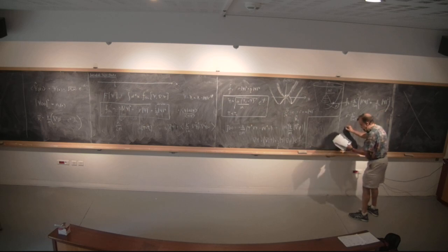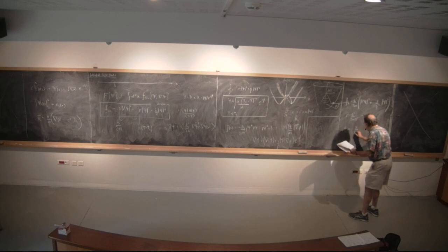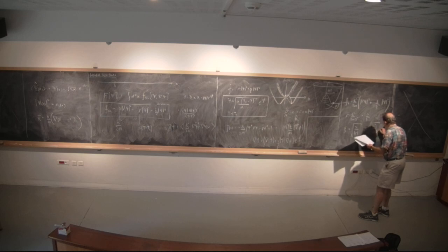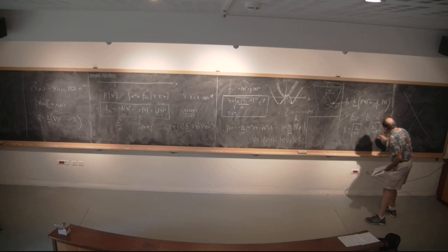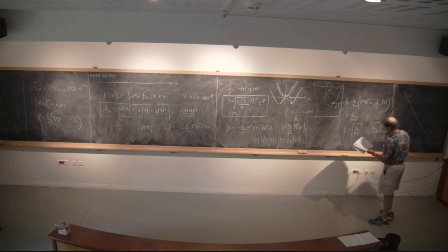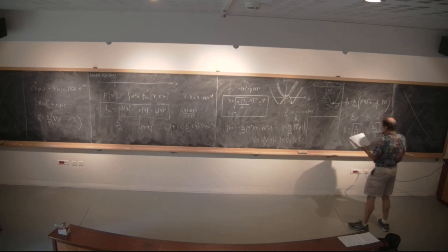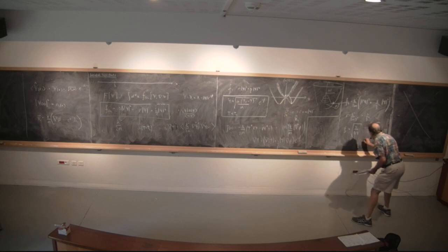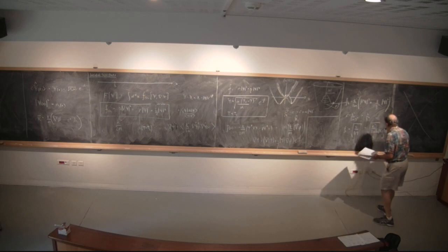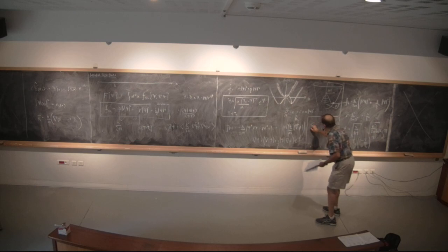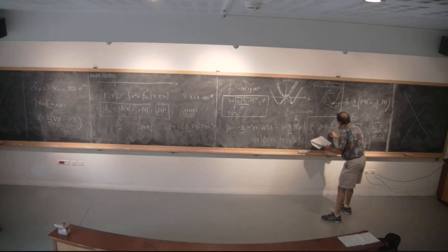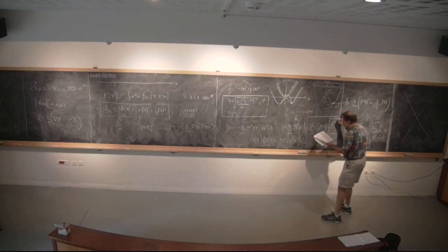And therefore you can see that xi is equal to the square root of s over the modulus of r, which is h bar squared over 2m modulus of r. Okay? And in fact, r is a times T minus Tc, so I'm going to write it as Tc minus T. Okay? And good. And we can also write that in the following form, as xi naught times 1 minus T over Tc to the minus a half. Okay? And this quantity xi naught is the zero temperature coherence length. It's xi at T equals 0, which is h bar squared over 2m a Tc. Okay, that is the coherence length.